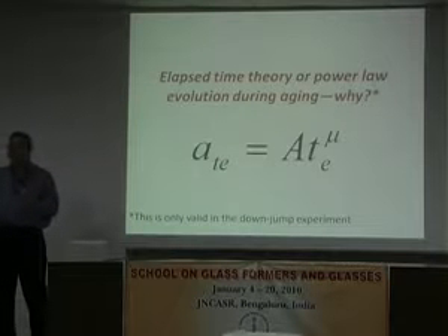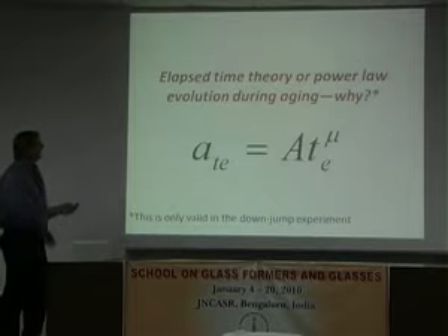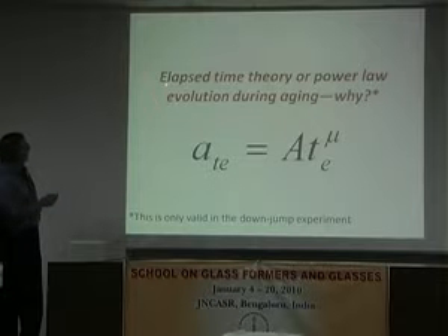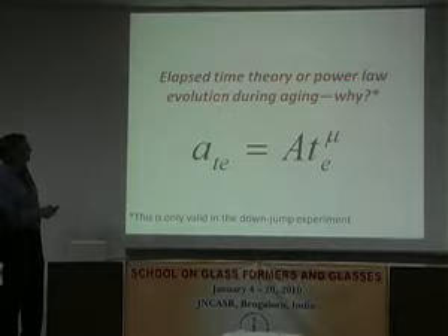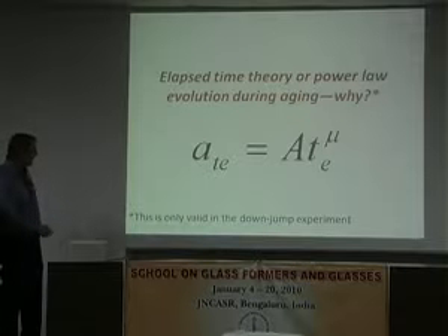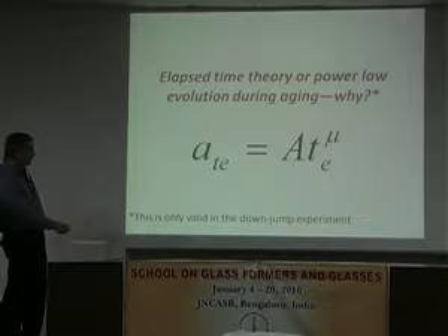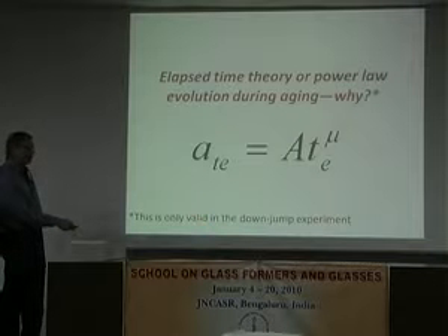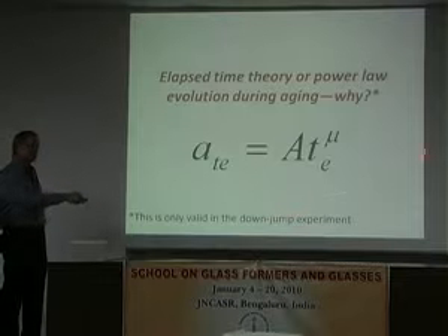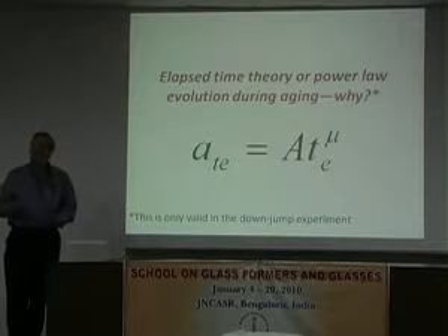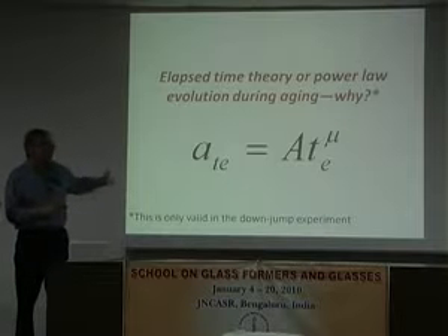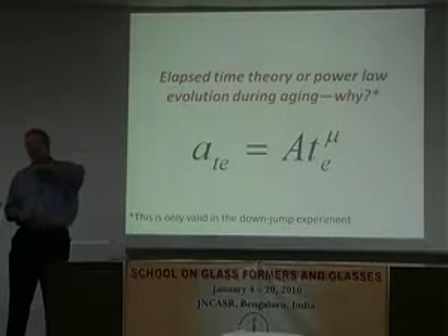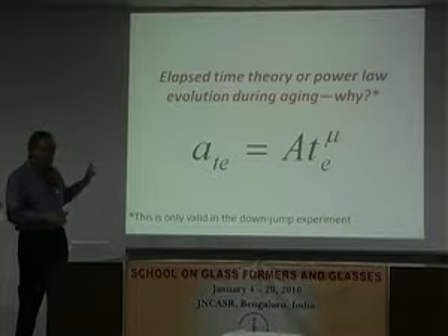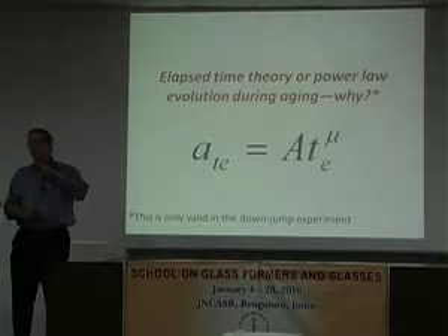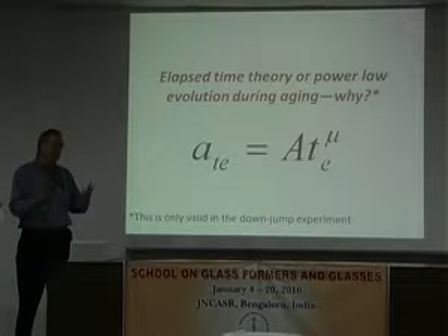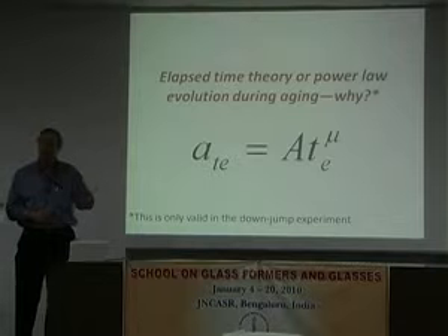So before that, I want to take into account here some issues related to elapsed time theory or the power law evolution during aging. And the question is why. And I put that star there to say that this whole thing is only valid in the down jump experiment to write things this way. When you do more complicated histories, obviously the elapsed time theory itself, according to the full-blown version, is valid, but when you're looking at, say, shear melting in a colloid, it can only be something equivalent to this down jump experiment, because everything goes always in one direction.